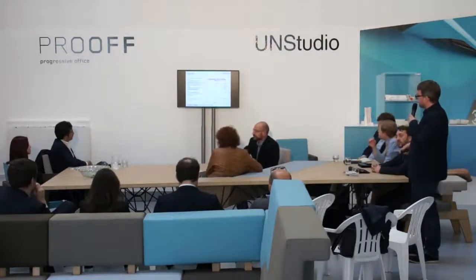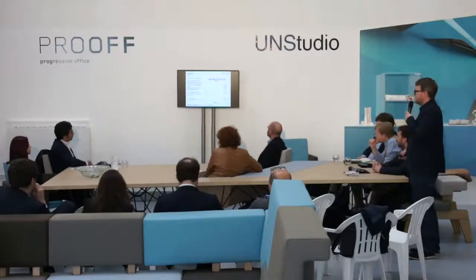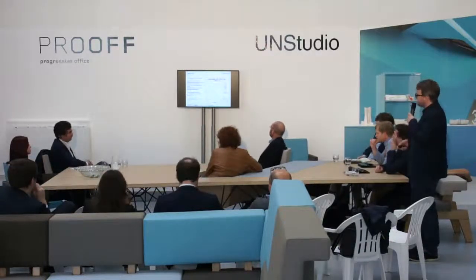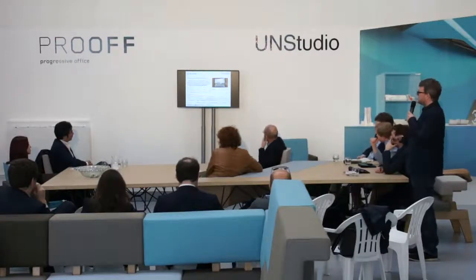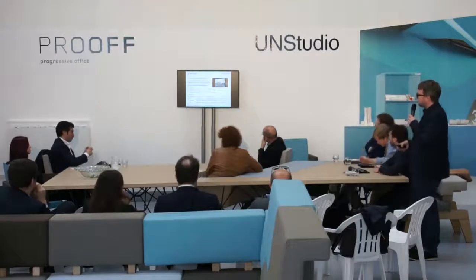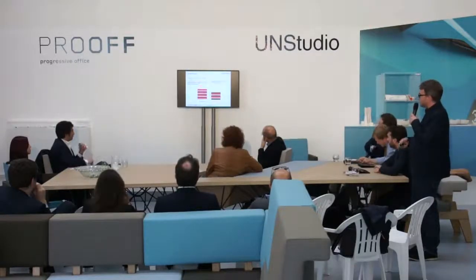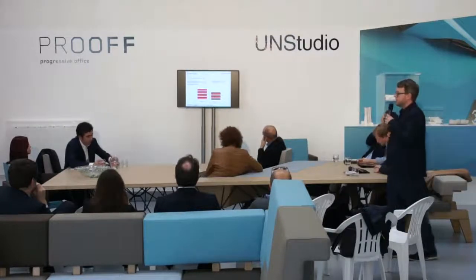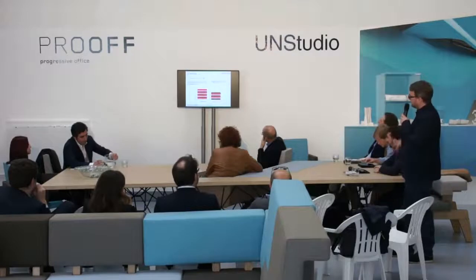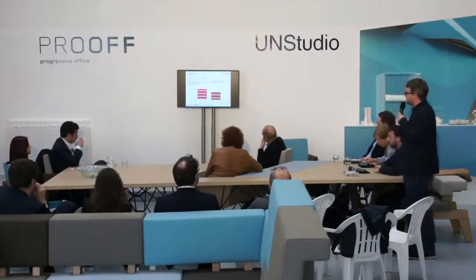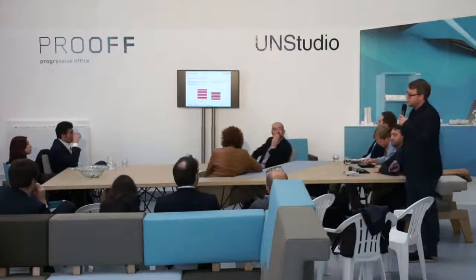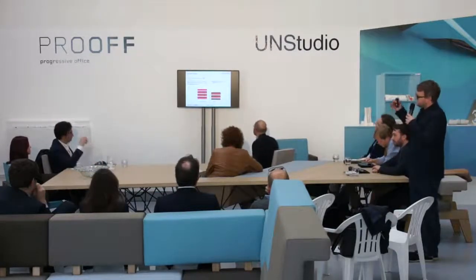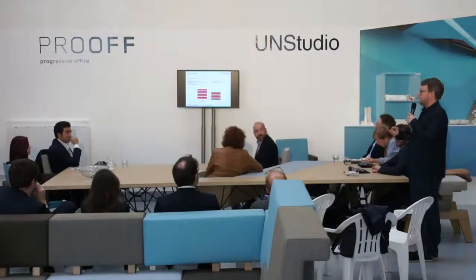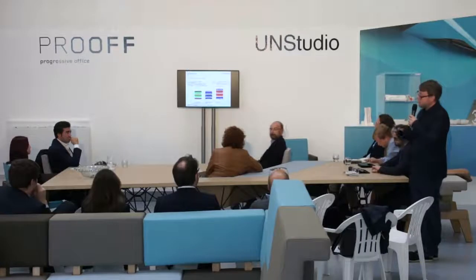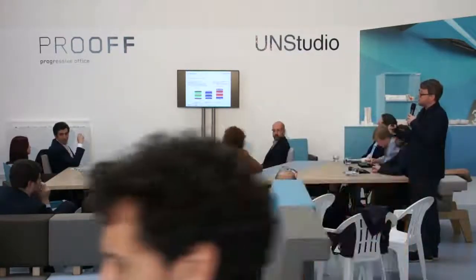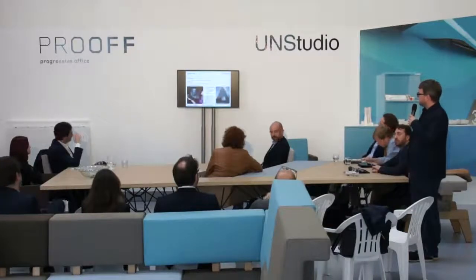So this is just a little bit more about the fail-safe and how we then looked at how it performs against regular panels, against its strength and its stiffness. It's not that dissimilar to that, so you're not looking at much benefit in terms of that. You're looking at how it combines in color and some of the other things we looked at. Blast resistance, we found that to get the equivalent piece of glass doing the same level of blast, you'd be looking at 4 layers of regular glass against 2 layers of regular glass with a Gorilla Glass core. So you could end up with much thinner bomb-resistant or blast-resistant glass than you might traditionally otherwise have had. Traditionally, where it's combined with acrylics, you get problems with scratched surfaces and things like that. So that's where that comes to.